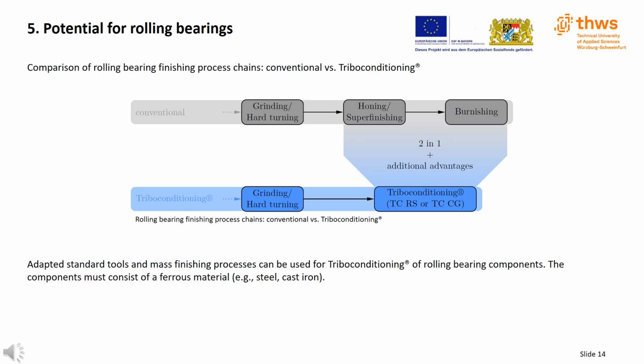With triboconditioning, the last mentioned processes of superfinishing and burnishing can be combined in one. Like superfinishing, triboconditioning improves the surface quality, and like burnishing, triboconditioning changes the surface composition by incorporating iron oxide FeO. In addition, a solid lubricant such as tungsten disulfide is produced. Adapted standard tools and mass finishing processes can be used to apply triboconditioning to rolling bearing components. The only requirement is that the components must be made of a ferrous material, for example steel or cast iron.